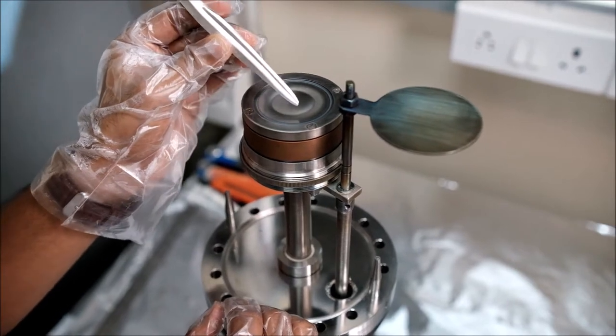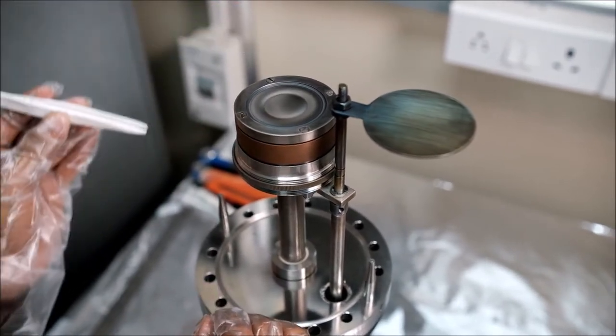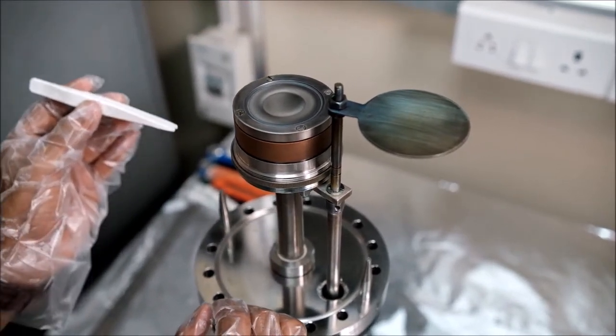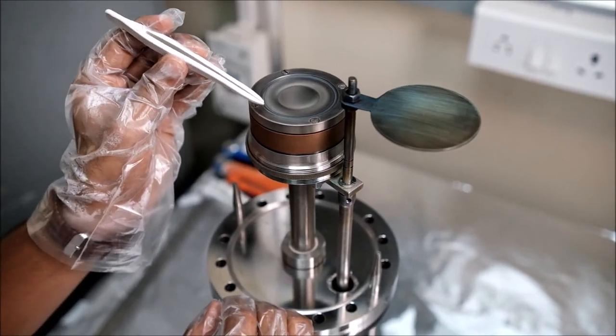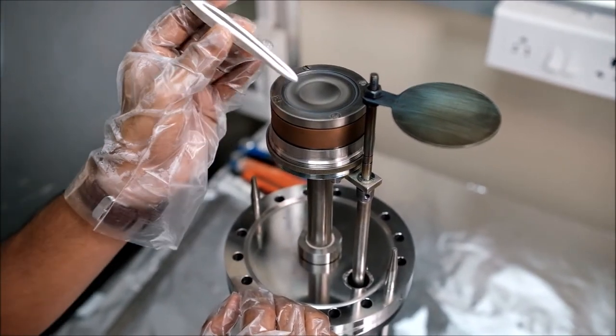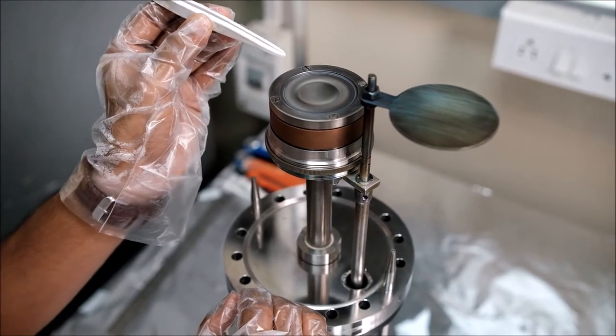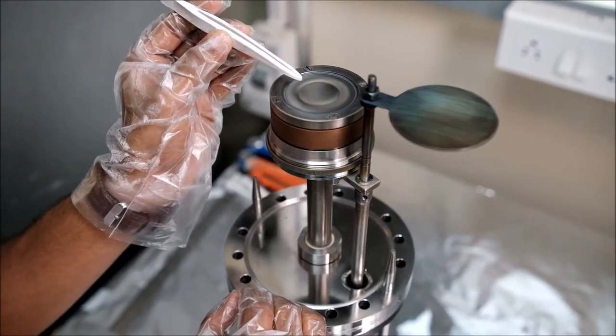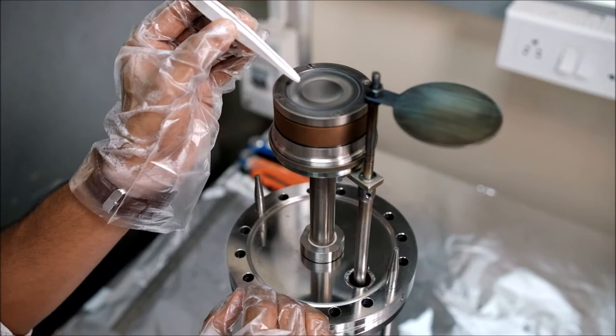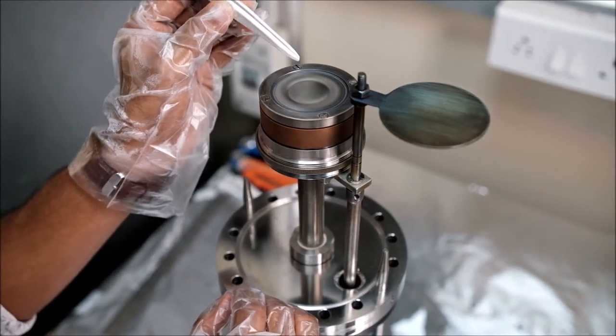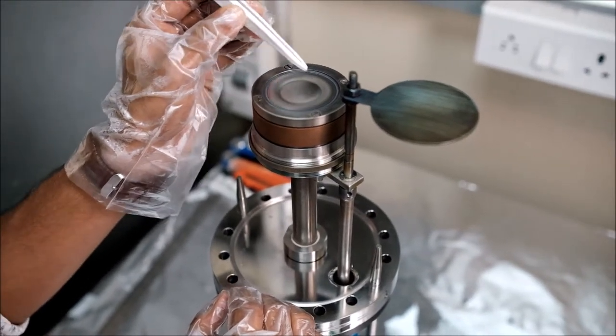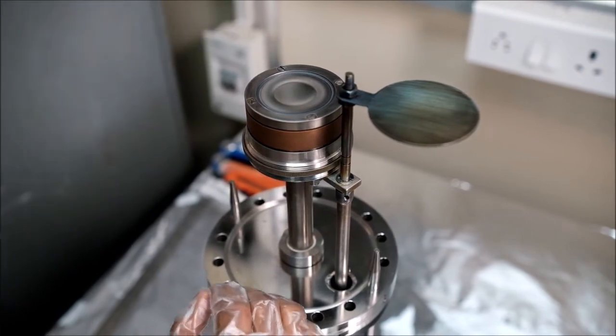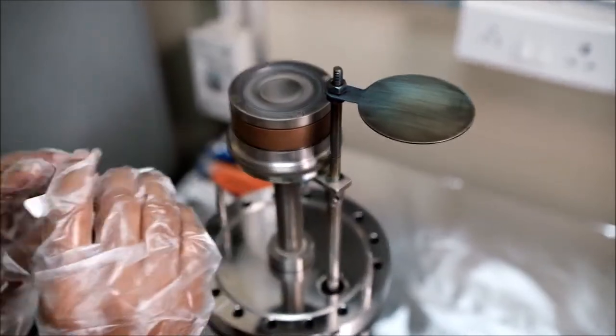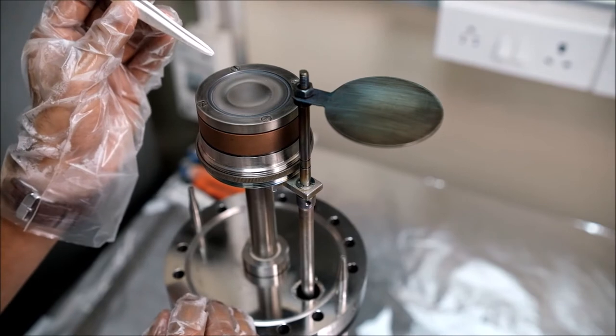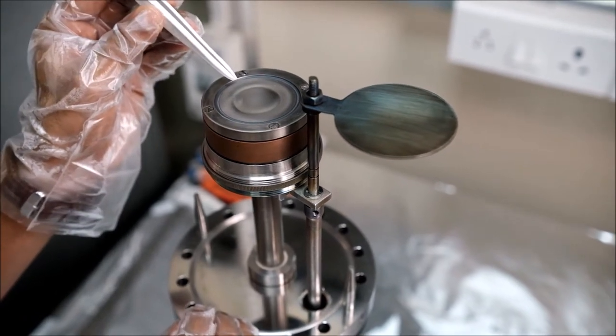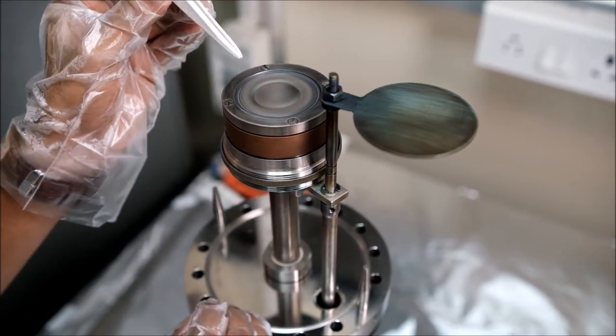While explaining the magnetron position, I explained how the magnetic field is aligned, and because of this magnetic field, most of the argon ionization occurs in this area only. That's why most of the sputtering occurred in this zone, and we see there is a grooved structure on the target. And also we do see at this outer part there is not much sputtering happened.